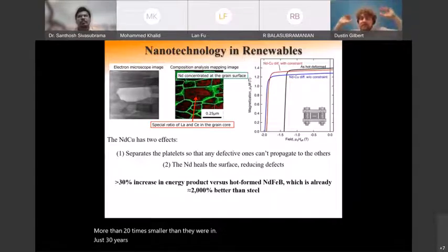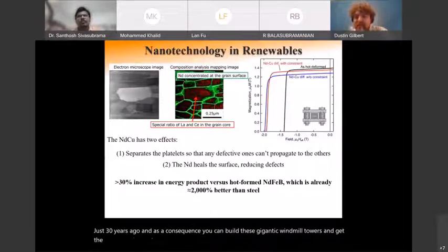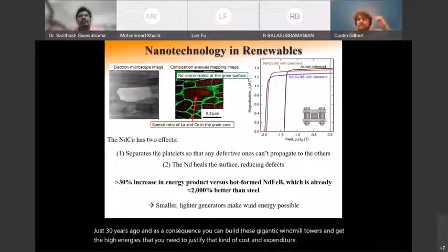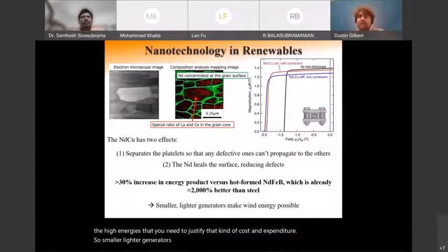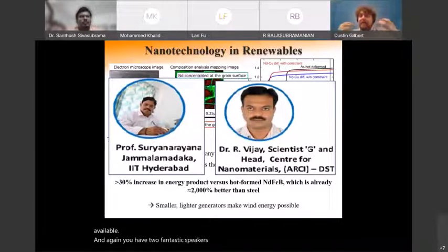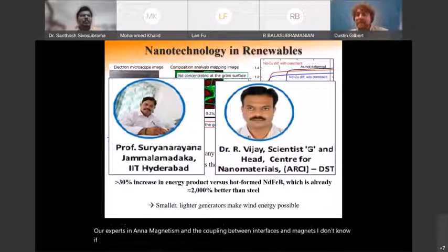And as a consequence, you can build these gigantic windmill towers and get the high energies that you need to justify that kind of cost and expenditure. So smaller, lighter generators make windmills possible, make this renewable technology available. And again, you have two fantastic speakers there that are experts in nanomagnetism and the coupling between interfaces and magnets. I don't know if either one of them are going to talk about neodymium and iron boron, but they're absolutely able to because they know an extraordinarily large amount about the coupling between magnetic layers and interfaces.